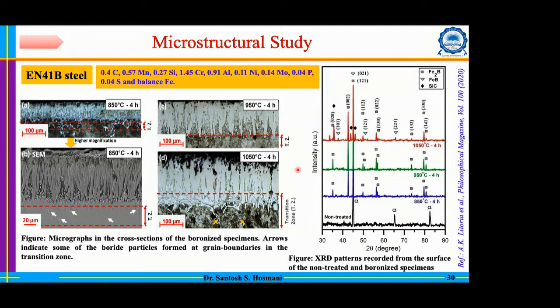Only the temperature is different. If you notice, at a low temperature of 850 degrees Celsius, the boride morphology, if you compare figure B, which is an amplified view of figure A, with figure D, you can see a significant difference in their appearance. In figure B, the borides are very thin in nature and very sharp in appearance. However, at a very high temperature, 1050 degrees Celsius, these borides are not very sharp; blunted tips are there. And if you go to the lower temperature, 950 degrees Celsius, the tips are very sharp again. That means the boride morphology is significantly dependent on temperature.